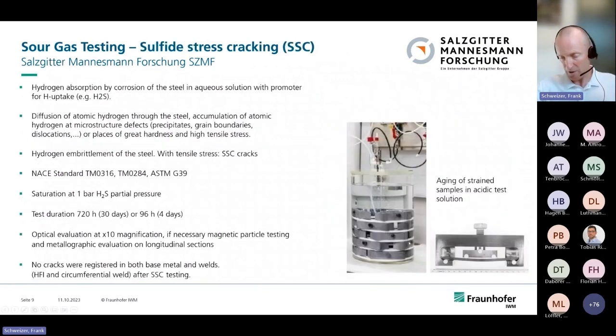Also, you can take out samples like this and put them under stress, for example by a four-point bending machine, and put this also into a 1 bar H2S partial pressure, for the same duration or an extended duration of about 30 days. And you do an optical evaluation, or you can do magnetic particle testing to see if there are cracks building up in the materials. And for the X56 steel, the ferritic steel we investigated, there were no cracks registered in the base metal or the weld metal, for all welds we had. So this was also very good.